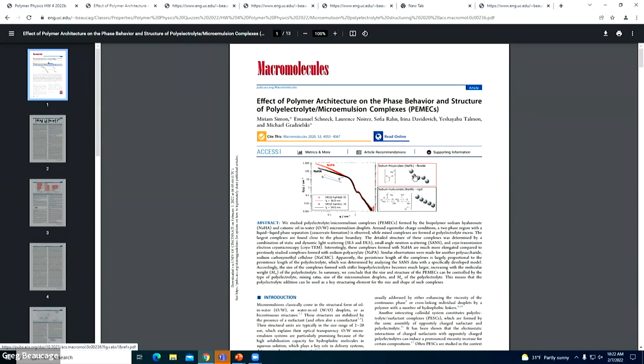When it kinks up, dmin is going up. So he gets 1.5 for the red one, the green line. That means it's a kinked rod. I mean, it could be a kinked rod. It could be other things. It can't be a sheet because it's less than 2, right? But it could be other things besides a kinked rod. It could be a branched rod, for instance, or something else that you can't imagine. But one thing it could be is a kinked rod. So it doesn't tell you exactly, but it's consistent with this cartoon that he has.